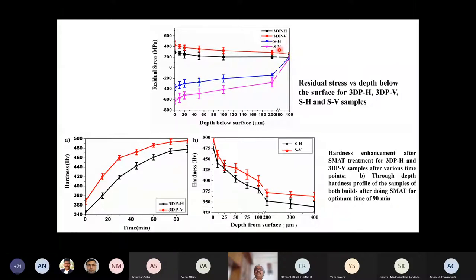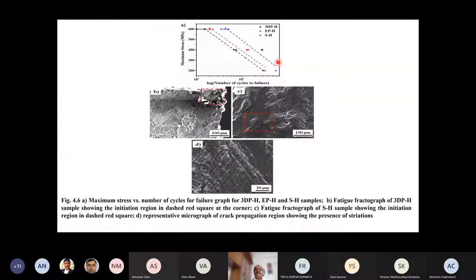SH here represents the case when the horizontal and vertical builds were SMAT treated. So the SMAT treated material is showing this curve, and we could see that there is a very substantial improvement. This is a logarithmic scale, so you can see we have not even seen failure occur almost up to here. So the life of the material has increased by several powers of ten as a result of surface mechanical attrition treatment. There was some improvement in terms of heat treatment also, but SMAT has really led to a very good result.